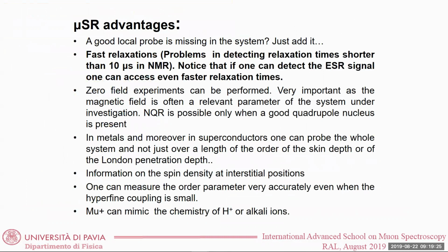Well, the advantage of MUSR is that you can measure relaxation rates which are quite fast, while typically if you do, for example, NMR, okay, you cannot access relaxation times which are below usually 10 microseconds, something like this. This is just because of some technical aspects related to pulsed nuclear magnetic resonance. And so in this case, okay, it is convenient to do a MUSR experiment. Let me give you some examples.